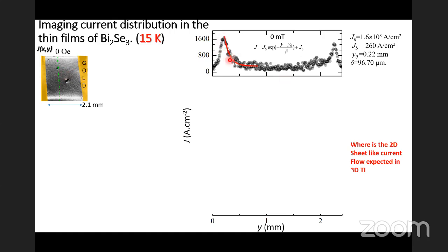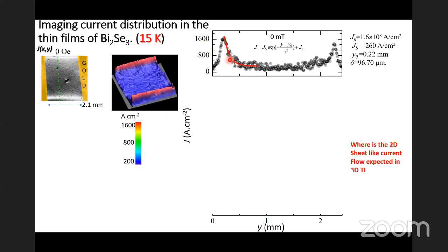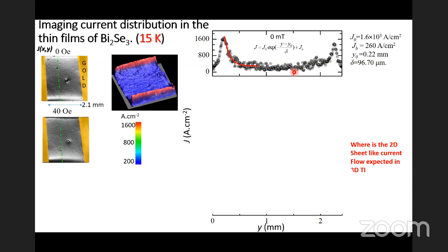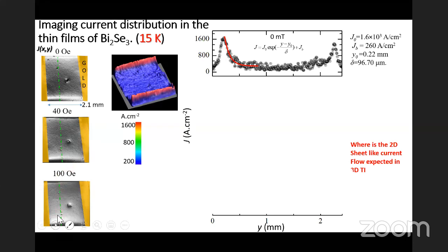Now what we did was that we applied weak magnetic fields. This is a three-dimensional map of the current distribution. You can see that on the edge there are strong currents, and then it decays down to about 200 amps per centimeter square in the center, and this is uniformly present all across the film. Now if you apply a magnetic field, what you find is that the currents on the edges are slowly decreased. You start decreasing the currents which are on the edges, and this is 40 Gauss, and at 100 Gauss you get almost a uniform current distribution all across the film.